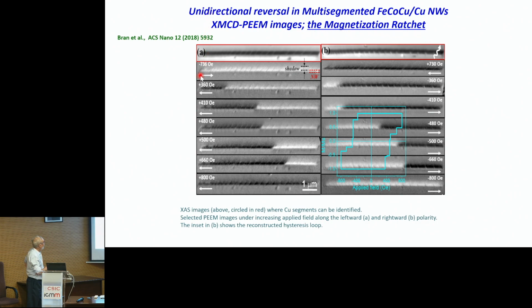So under a negative field of -700 Oersted, we have a white contrast. So the white is practically saturated magnetically. And as we apply a positive field with increasing amplitude, we observe that the reversed domains increase in size until getting the opposite saturation. But interestingly, the reversal starts in the end of the nanowire with the smaller